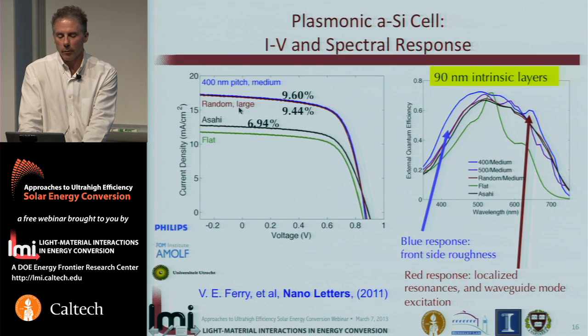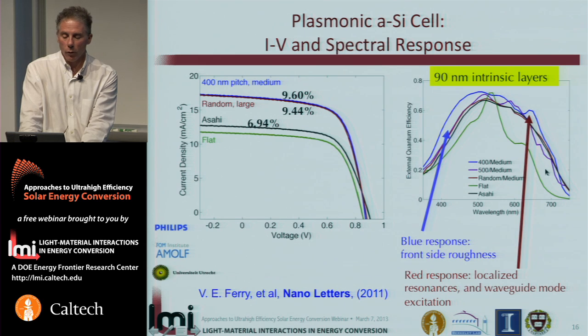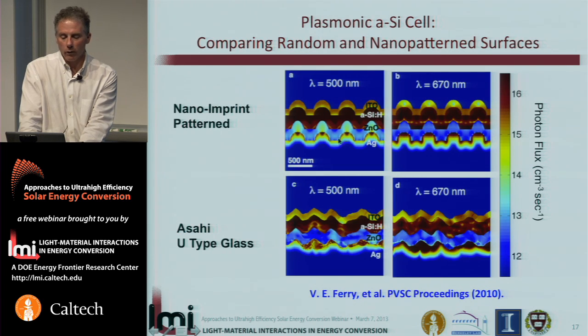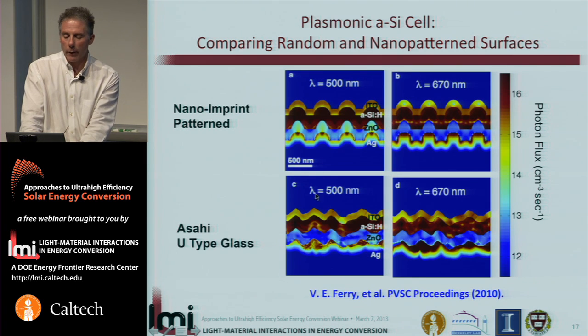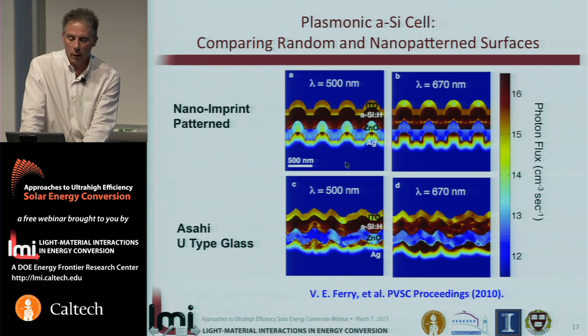So this simply shows that by optimal design of these plasmonic back reflectors, it's possible to achieve substantial increases in photocurrent that are manifest in the spectral response in terms of an increase in the blue response and the red response, due to the reduced surface reflection and the excitation of these in-plane Bloch modes and localized modes that enhance the red response over that of a thin film cell otherwise. You can see this quite simply in terms of the modes that are excited, and a full wave simulation shows that the amount of power that's usefully absorbed in the semiconductor absorber layer is considerably higher at different regions throughout the visible regime than for a randomly textured back reflector. And this kind of full wave optical analysis allows us to understand the physics. For example, we see parasitic absorption in the metal in these sharp asperities on a randomly textured back reflector.